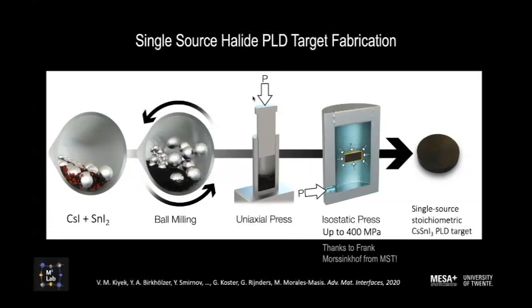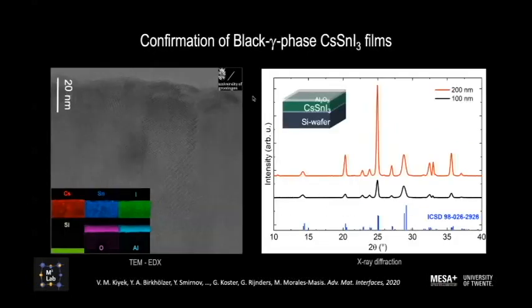This is a process flow starting with cesium iodide and tin iodide, and using the right solid-state synthesis and the correct pressing, you can get a single-source stoichiometric PLD target. And that worked out quite well, as you can see over here. It forms the right phase. You have this cesium tin iodide in the right structure, as you can see on the right-hand side from the X-ray diffraction patterns, and you can also see that it's nanocrystalline. From the EDX data, you can clearly see that the thin film is homogeneous in terms of composition, in terms of the cesium, tin, and iodide.